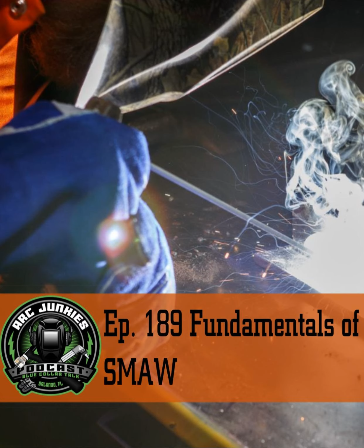Now I can look at a machine in my shop on the digital readout and tell you if somebody's arc length is too far out, because that voltage is going to increase, and I'm going to be able to see the amperage drop a little bit. I know roughly what amperage most of my students should be at, depending on the position we're working in. So if it's dropping lower than what they should have it set for, I know their arc length is too far back, and I can walk into the booth and say, hey, you need to tighten up your arc length, and here's why. And just walk them through that process.